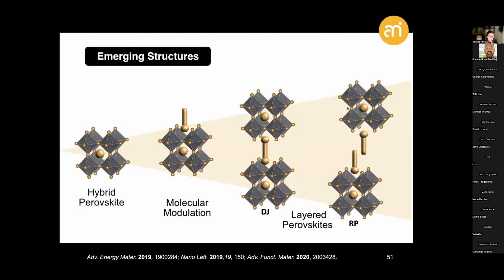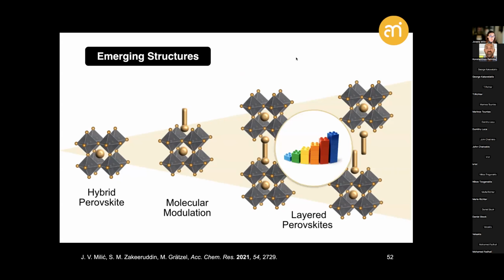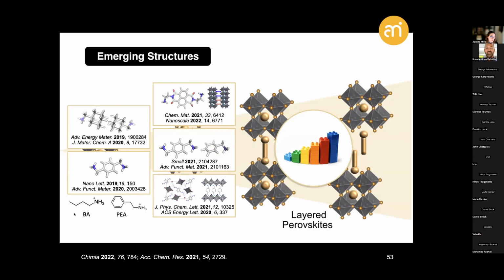In both cases now, the role of the organic material is even more important, as it not only templates the resulting hybrid structure, but the assembly of the organic component directly affects the structure and indirectly their optoelectronic characteristics, as well as the stabilities through both the hydrophobicity of the organic component as well as their ion impermeability, which we have analyzed over the past few years by looking into a number of different spacer components, which conventionally involve this typical butylammonium alkyl chain or phenylethylammonium based species, both corresponding to the Ruddlesden-Popper phases, which we have extended in a number of other aromatic or carbocyclic systems, including adamantyl for van der Waals based interactions, or different types of small aromatic or extended aromatic units for, in particular, Dion-Jacobson architectures.